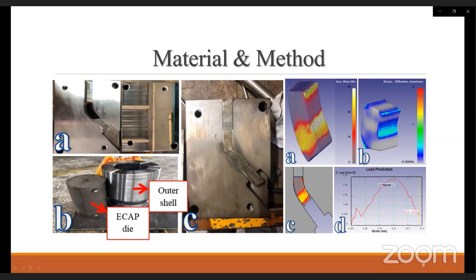The samples are solutionized at 525 degrees centigrade for 2 hours before ECAP. After solutionizing, the samples are pressed at 12 mm per second and at room temperature. We have selected graphite powder in spherical shape as a lubricating agent instead of molybdenum disulfide, because molybdenum disulfide has a rectangular shape. At first trials, the samples pass through the turn at the ECAP die, but after that, the samples expand and fit to the channel.